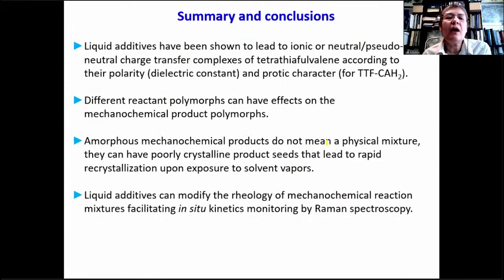So in conclusion, we have shown that liquid additives can lead to different ionic or neutral charge transfer complex polymorphs of tetrathiafulvalene according to their polarity or their dielectric constant, and sometimes according to their protic character. So they may have a role in the mechanism for the full or partial ionization of those donor and acceptor molecules. Different polymorphs of the reactant tetrathiafulvalene can lead to different polymorphs of the product, and that is something that is not often seen in literature, in publications.